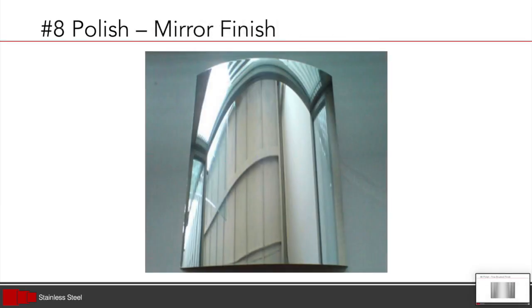And then we have the number 8 polish finish, which is a mirror polish. As you would imagine, it will result in a highly reflective finish. Mirror polishing requires a significant amount of buffing to achieve this reflective look. While polishing, great care must be taken to remove deep scratches. Any defects will show through and be quite noticeable once you reach the final stage. One benefit of a mirror polished stainless steel is that the finishing process improves the corrosion resistance. This is because it removes crevices where corrosion-causing chlorides can sit and do their work.